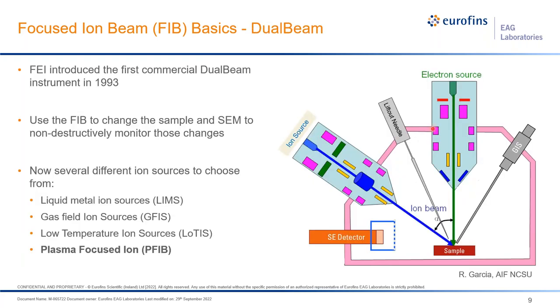So FEI introduced the first commercial gallium-based dual beams in the early 1990s. And a dual beam is essentially a merging of an SEM with a FIB, where we can then use the FIB to change the sample like we want, and then use the SEM to non-destructively monitor what we're doing. We can add other things like lift-out needles to do sample prep for TEM, and here's the GIS, where we're introducing gases at the surface, and then we have a variety of detectors to collect the signals that are formed.